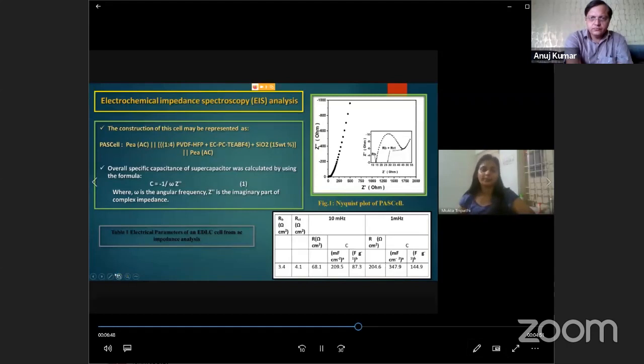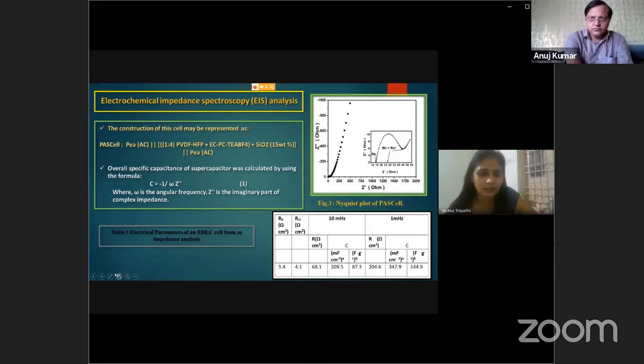So for supercapacitor analysis, we used three types of techniques: impedance spectroscopy, cyclic voltammetry, as well as charge discharge. Cyclic voltammetry and charge discharge we will discuss here. This is the impedance spectroscopy. In this part we used the cell, and the biomass based electrode has been sandwiched with the electrolyte system, which is the nanocomposite polymer electrolyte, and that combination of the fabricated cell has been further utilized for analysis.